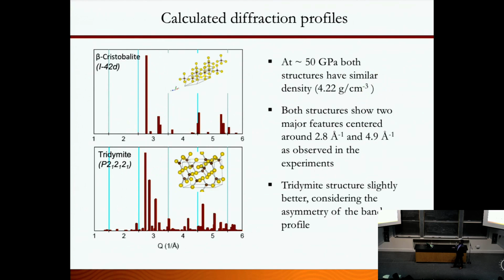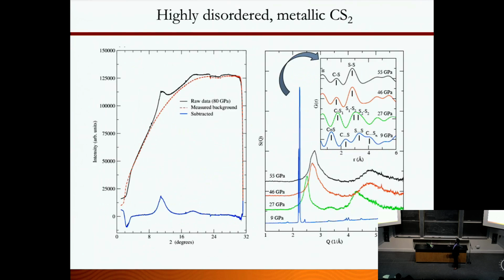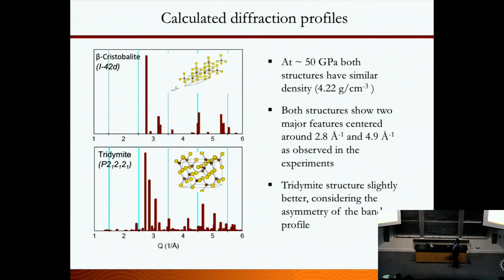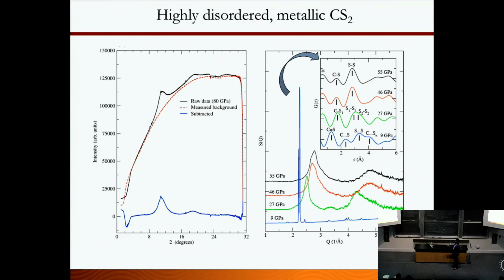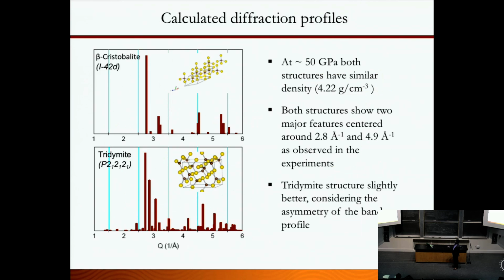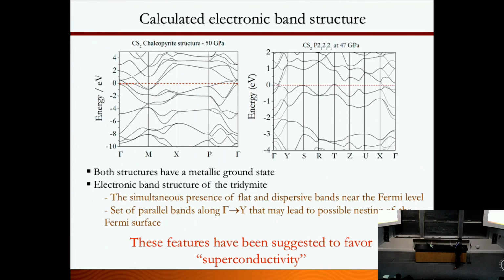And we did some diffraction profile calculation. So we have two different structure candidates based on CS2. From the diffraction profile, if you look at right here, the tridymite structure, the shape of this is very similar to what we experimentally observe right here. So we don't clearly know what type of structure, but the best guess we have is somewhere around something like a tridymite structure, 4-fold coordinated.